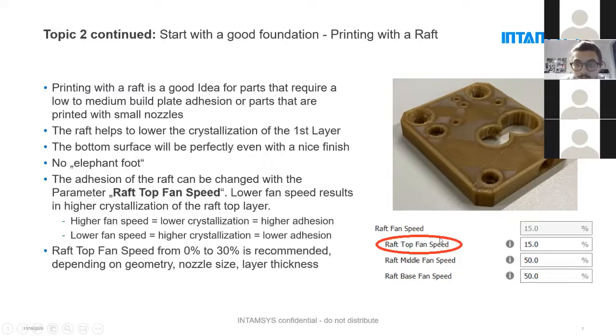It's very easy to keep in mind. A higher fan speed, the parameter is called raft top fan speed, results in a lower crystallization, which gives you then a higher adhesion between the raft and your part. And the other way around, a lower fan speed gives you a higher crystallization of the top layers from the raft, which gives you then a lower adhesion. In general, something between 0 and 30% is recommended, but this definitely depends on the geometry, on the nozzle size, and on the layer thickness from your part, and also on the layer thickness from your raft top layer, which is then again related to the nozzle size. So it's definitely not possible to give one value that works in every combination, but if you find one value for one combination, it works really, really good and very repeatable.